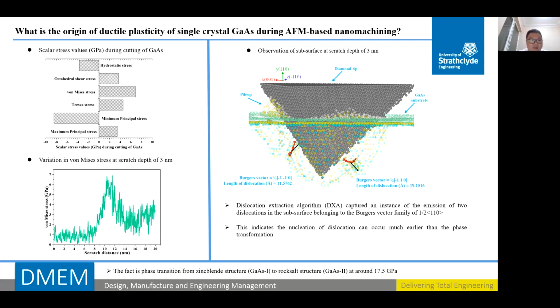Furthermore, I used the DXA method. As we can see, this method was used to capture an instance of emission of two dislocations in the subsurface. It shows a Burgers vector family of 1/2 <110> was found, as shown in this figure.